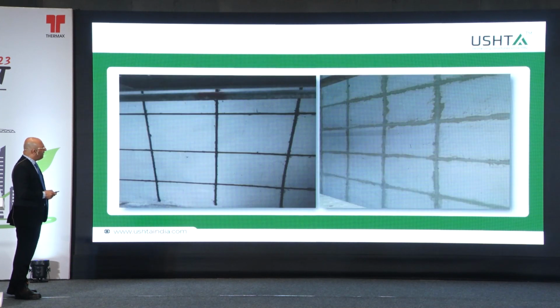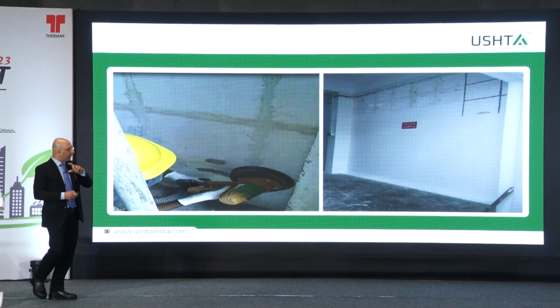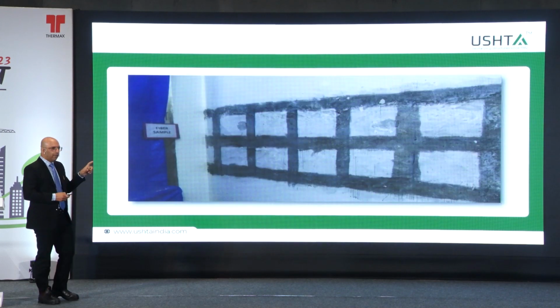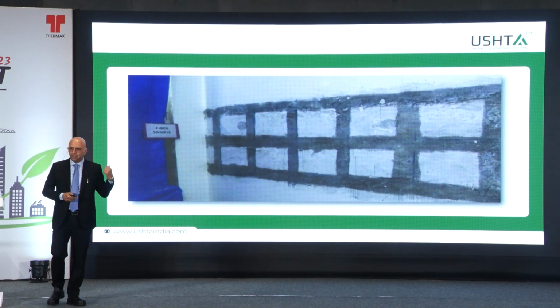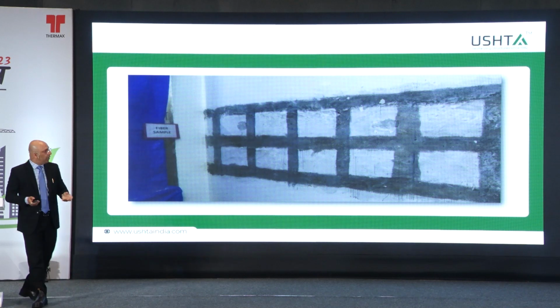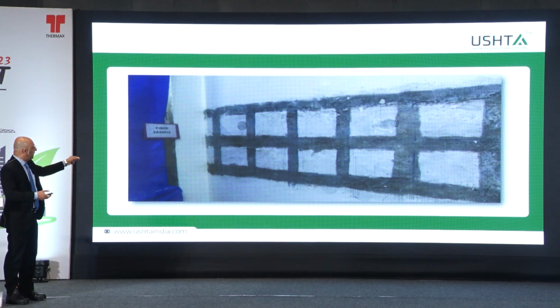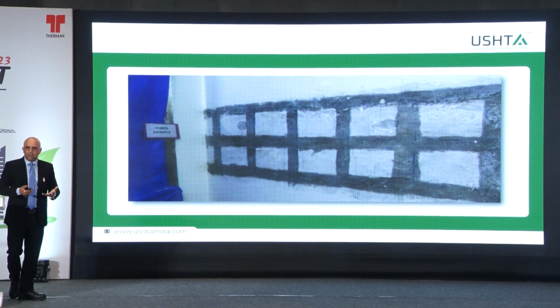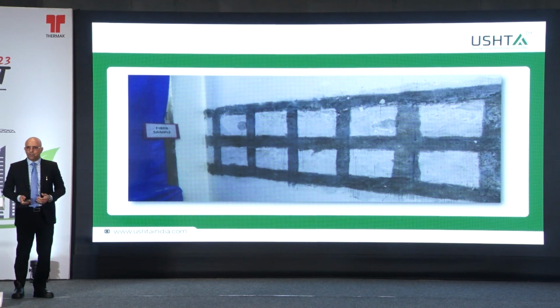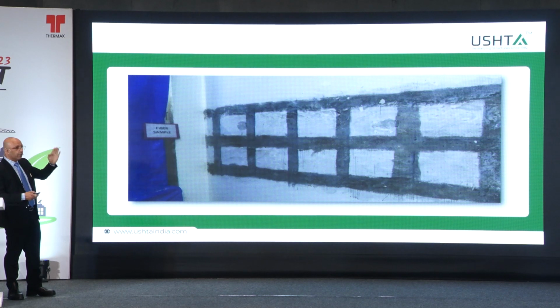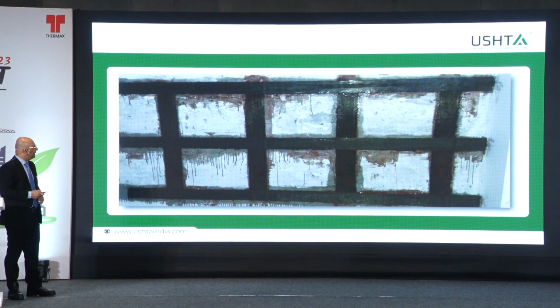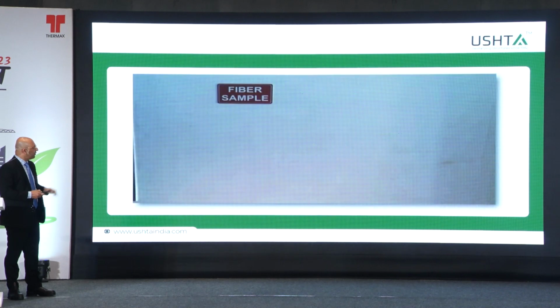And similarly in fiber, instead of covering it with the entire band which you saw in the blast proofing case, here our requirement was not that big. So we used bands 100 mm wide at every 400 mm center distance. That was sufficient for us. And anchoring was done on the side by fiber anchors. These are the steps. Earlier we did some samples outside the premises for testing, and the similar was replicated inside the plant.